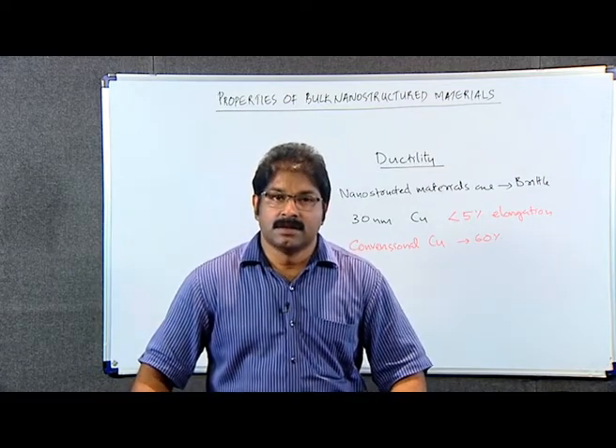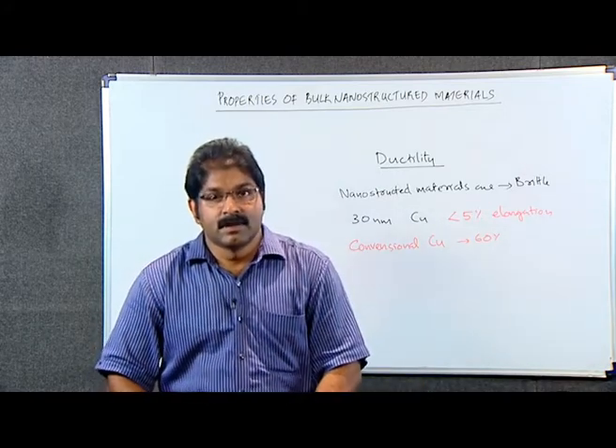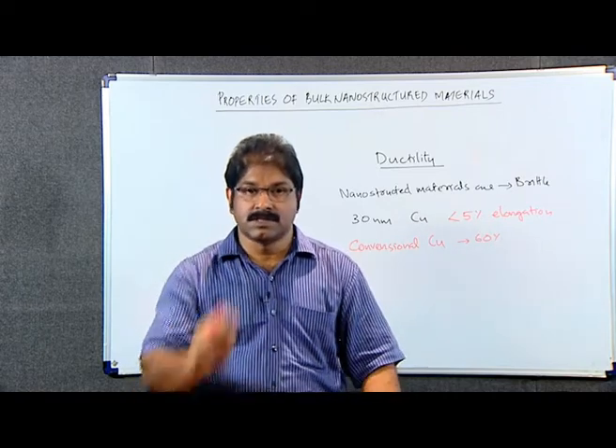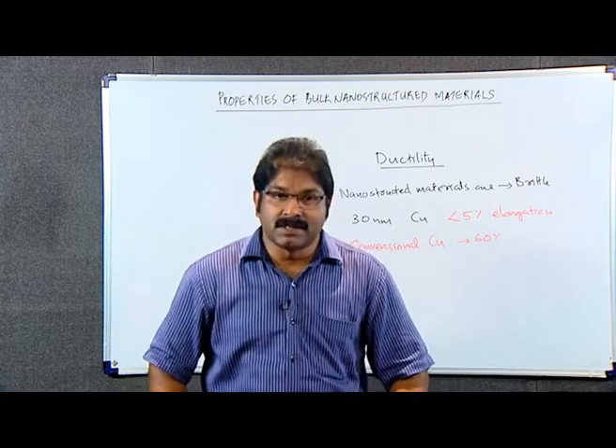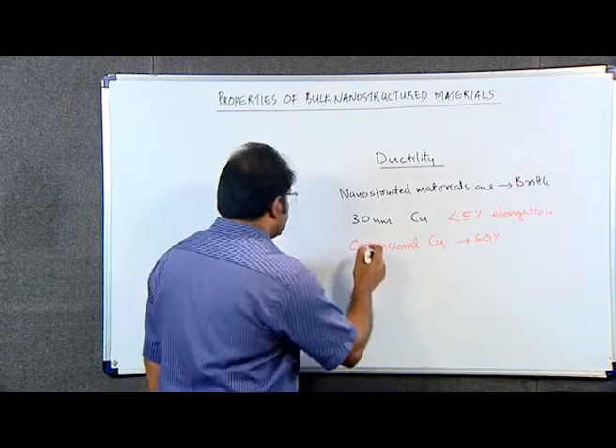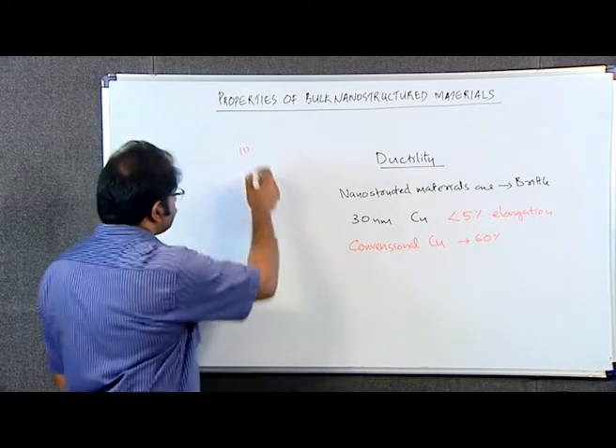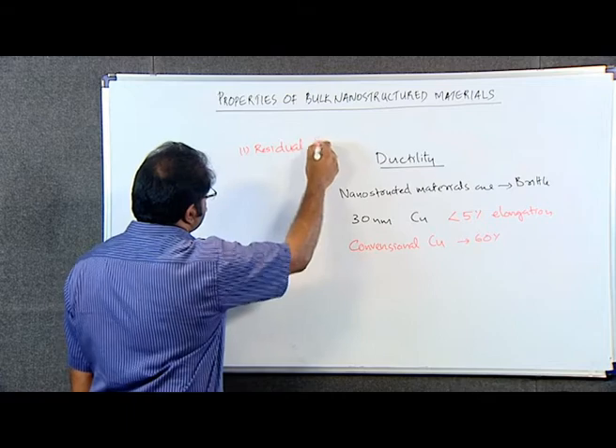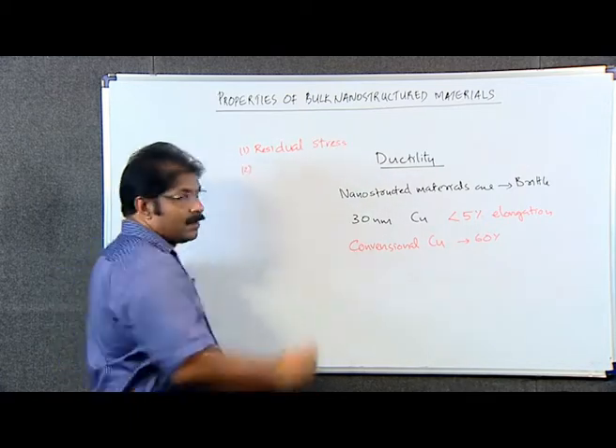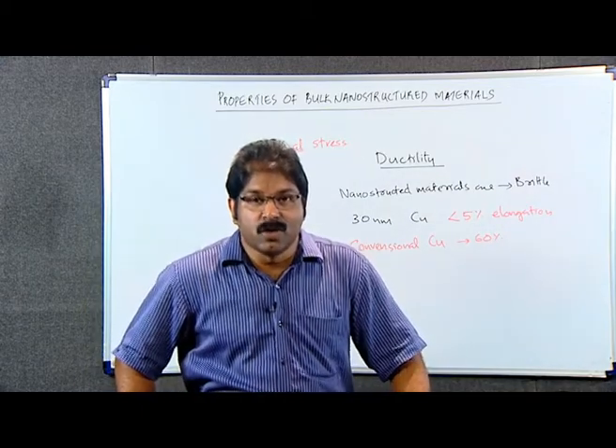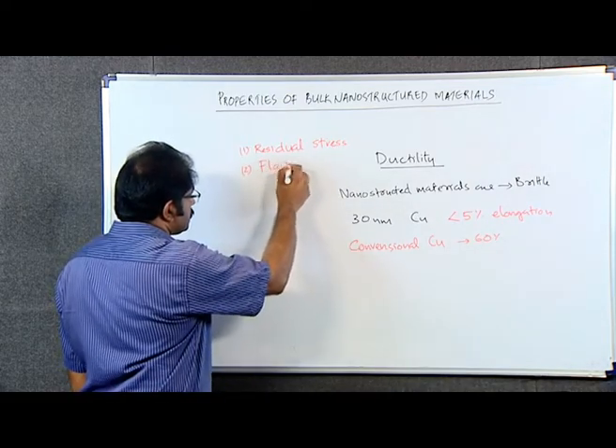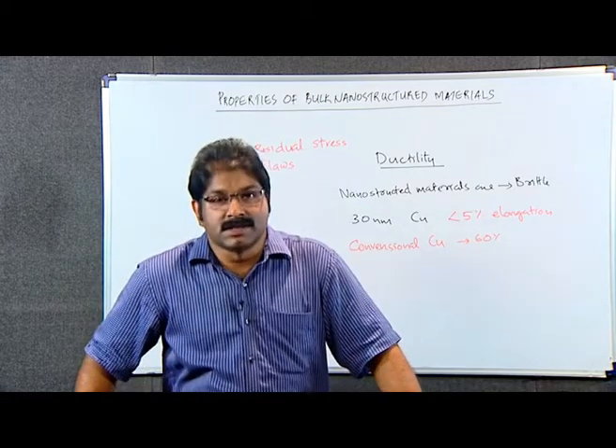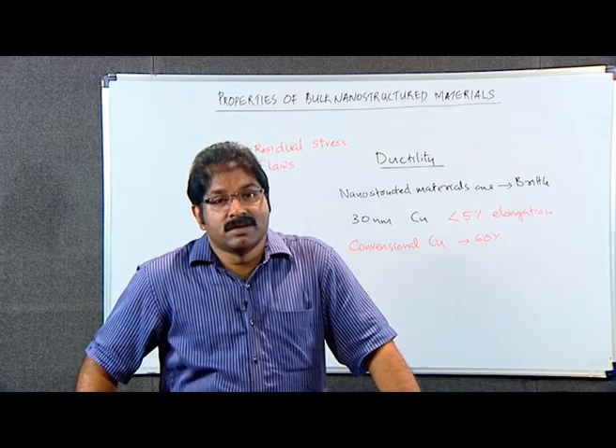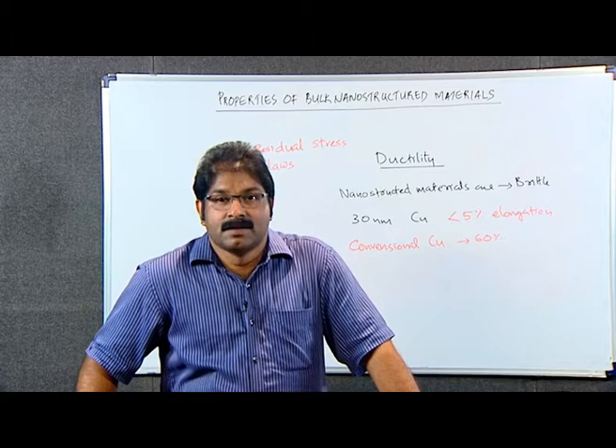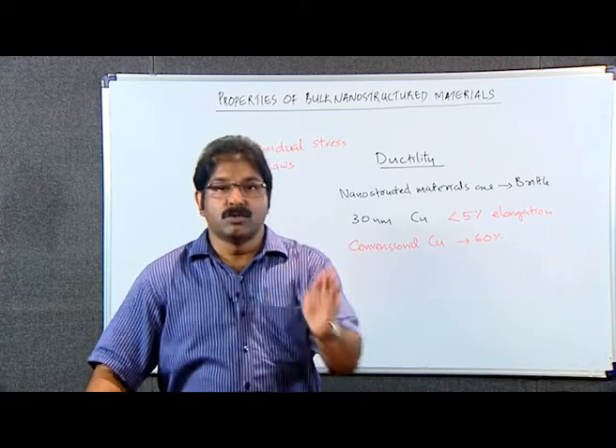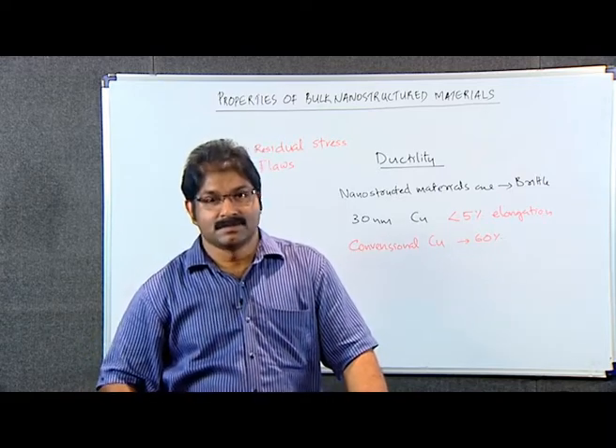What is the reason? The copper sample of nano-sized grains is a consolidated particulate sample, which possesses two main properties. At first, they possess large residual stress. And they will have a lot of flaws. And these two are the reasons for the brittleness of nano-sized grain materials. The residual stress and flaws restrict the dislocation movement and make the material brittle.